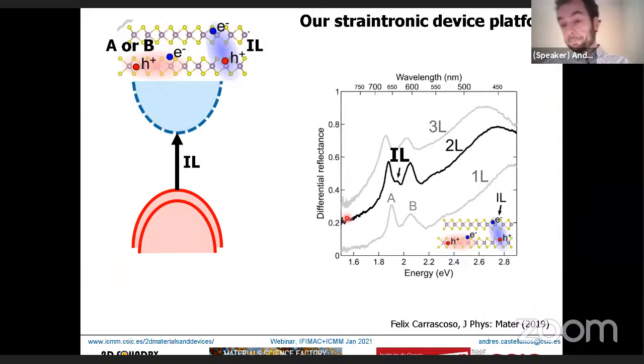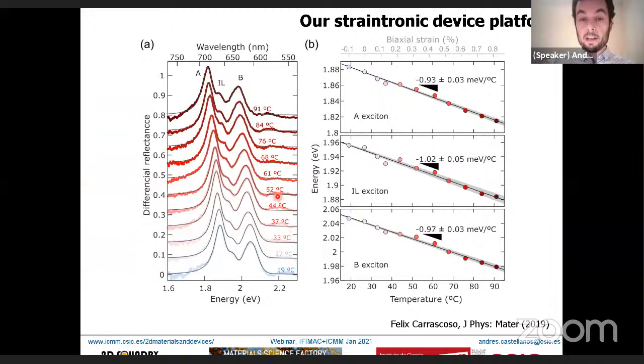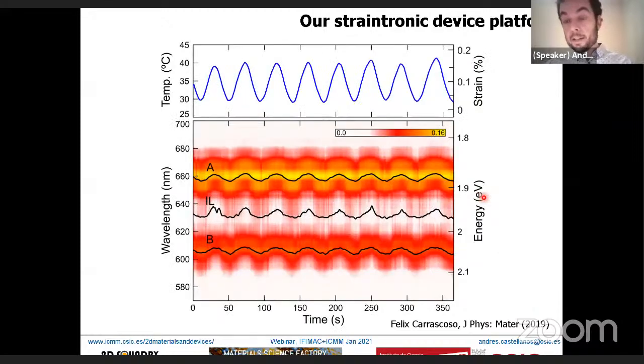We can monitor changes in the band structure of our material by examining this differential reflectance spectra as a function of strain, as a function of substrate temperature. We can change the temperature of the substrate and monitor the energies of these peaks, seeing how they shift upon heating. On this axis we have the corresponding biaxial strain - this is the substrate temperature, which we can correlate with biaxial strain knowing the thermal expansion of the substrate. We can see how we're able to gradually close the band gap, reducing it as a function of the biaxial strain applied to our crystal.